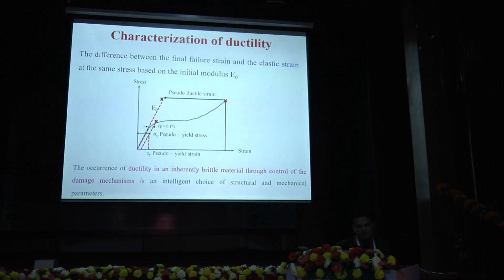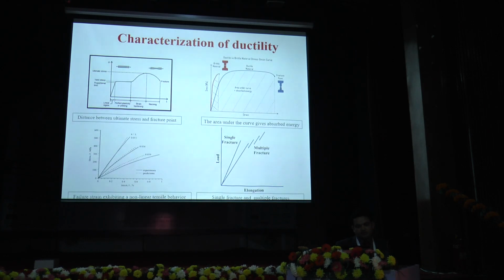So for ductility measurement, you can see from this curve the final failure strain, the difference between the final failure strain and the elastic strain at the same stress level at which we measure the initial modulus. Therefore, achieving ductility in an inherently brittle material through control of damage mechanism is an intelligent choice for structural and mechanical parameters of composites. These are the different ways to measure ductility.